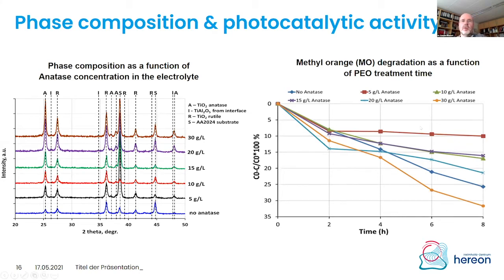And if we look at the photoactivity on the surface, we see that for the 30 grams we actually reach better performance. Surprisingly, and we still don't know why, if we do not add any anatase, the 10-minute treatment which we have performed is the second best in photocatalytic activity.